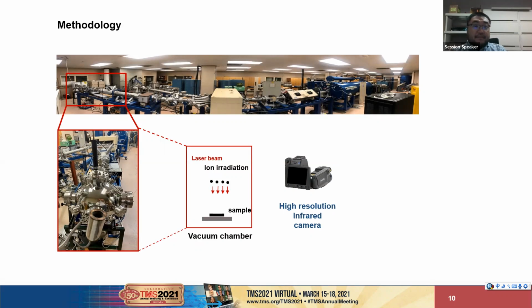Okay. This is the methodology of the in-situ thermal property measurement. As you can see, this is the overview and the side view of this tandem accelerator, and it's going to work this way. Instead of measuring the thermal property in a traditional way, our method combines the ion irradiation, laser beam, and infrared camera. When you shoot the laser on the surface of the sample, it forms a very tiny hot spot. Therefore, you are going to get a temperature distribution on the surface of the sample. This temperature distribution information can be obtained by a high resolution infrared camera. And by analyzing the temperature gradient, you should be able to get the thermal conductivity.